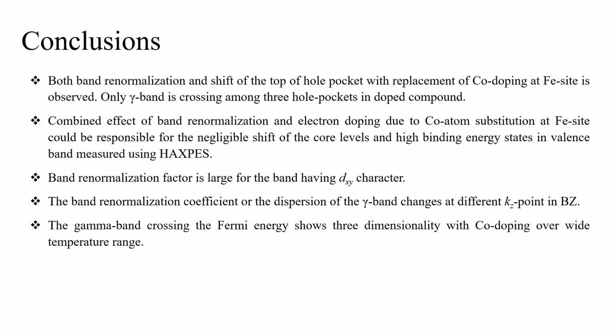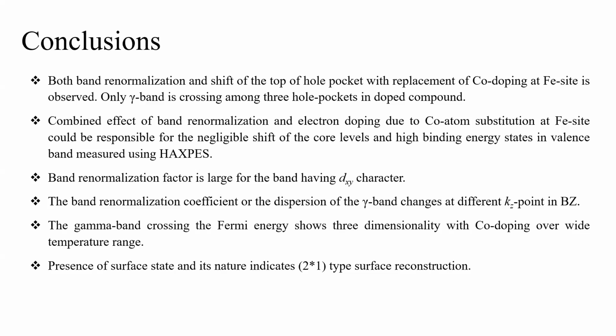The gamma band, which is crossing the Fermi energy, also shows a 3-dimensional behavior with cobalt doping over a wide temperature range. We also observed surface states in this compound, and by comparing with earlier spectra, we concluded that the surface states that we see in this compound are majorly due to a surface reconstruction of 2x1 type. And with this, I will stop my talk.